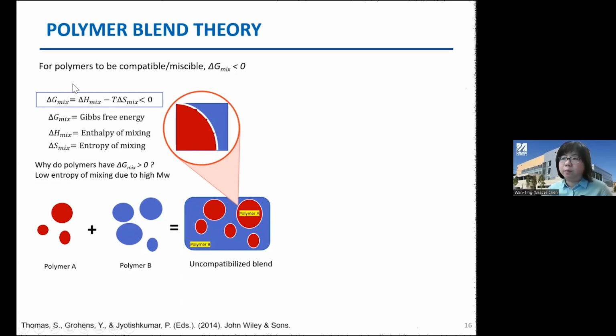And typically the enthalpy of mixing for polymers can be fine-tuned and further adjusted by adding some polymer additives to improve the interfacial interactions, which I'll talk about a little bit in a moment. And then the entropy here between two polymers, typically that is very, very small.